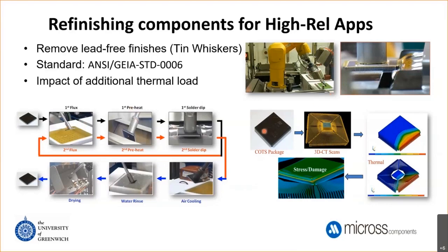And here we illustrate that here's the COTS package. There is interest here in optimizing the refinishing process in terms of those thermal gradients that the component will see as it's placed in the hot solder bath and removed. Of course, when we think about the die, those thermal gradients, 3 degrees change per period of time, we want to keep the die within those safe limits when we apply these additional thermal loads. But also, what is the impact of the internal construction to these thermal loads.